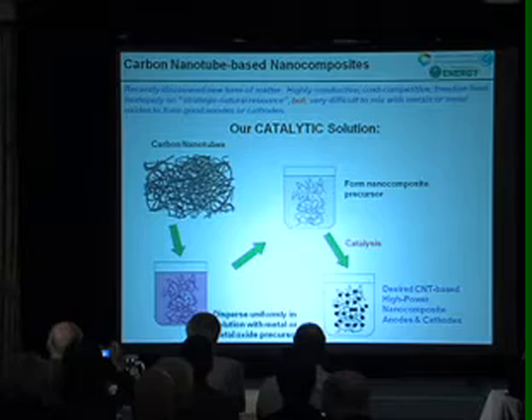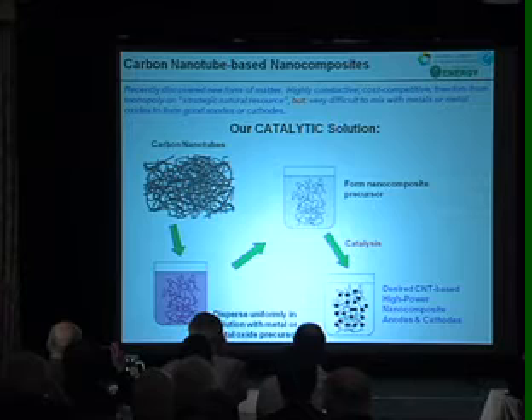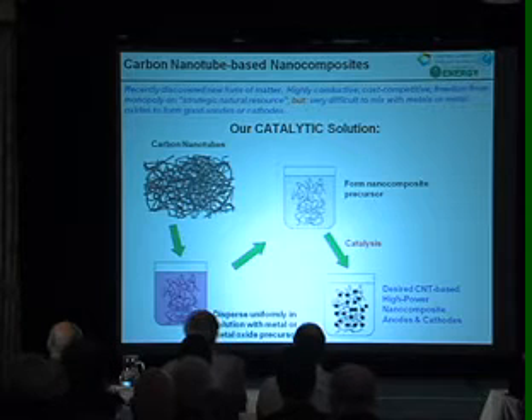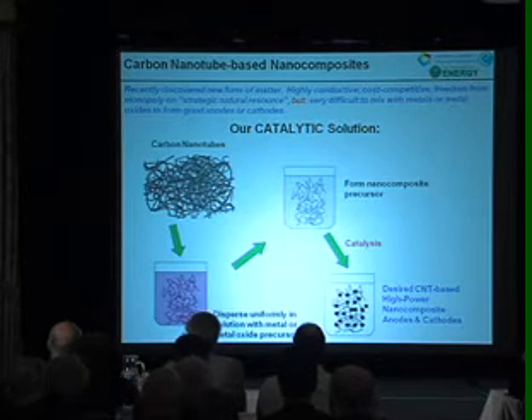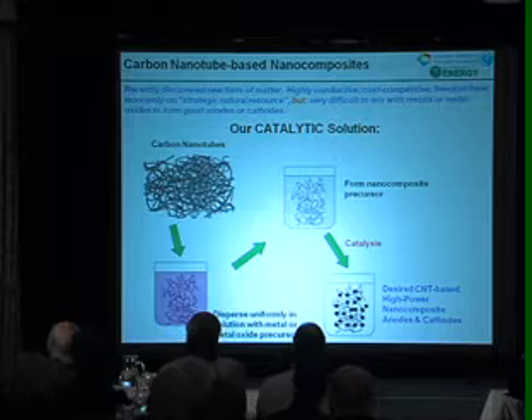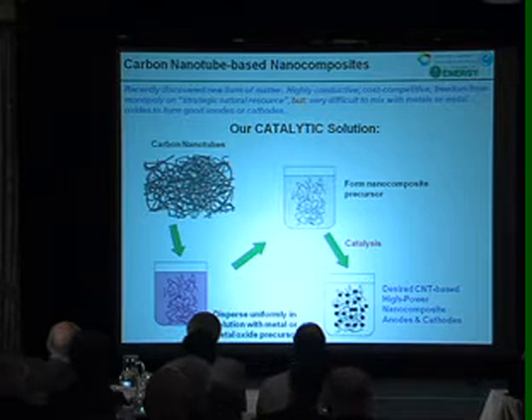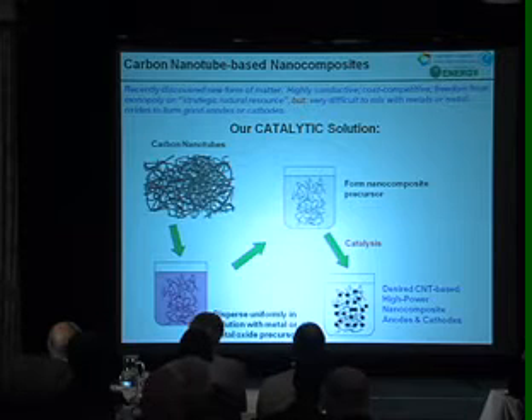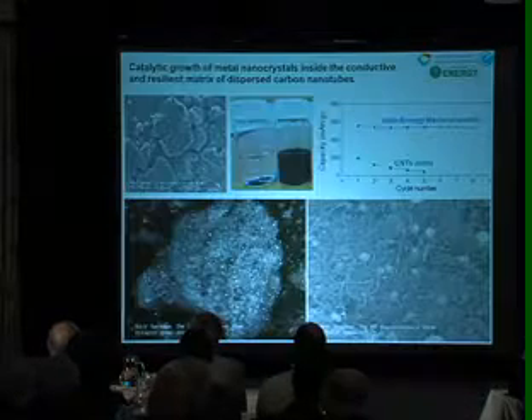But it's been very difficult to mix carbon nanotubes with metals or metal oxides to form good anodes or cathodes. We're extending our catalytic solution, just as I had described before. We suspend and disperse the carbon nanotubes uniformly in a solution of a precursor that we will then catalytically convert to the desired either high power nanocomposite anode or cathode. So it's just an extension of what I had shown you before.